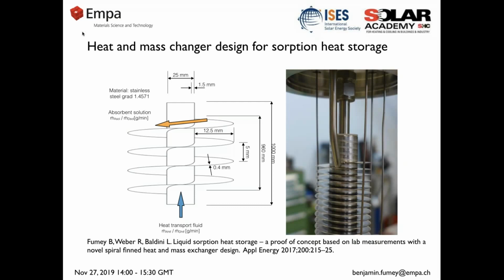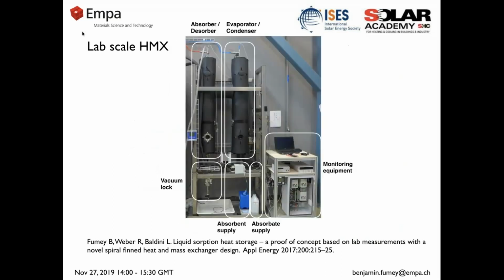And we've done numerous tests with this. For example, we have an exposure time of the sodium hydroxide of about 12 minutes in an ice counterflow, so we're able to cool down the sorbent right to the input fluid temperature and reach a continuous process and reach a maximum temperature gain, gross temperature lift, because there's always fresh sodium hydroxide introduced to the top of the spiral fin. And we've tested this now in a lab scale setup with a single tube, as shown here.